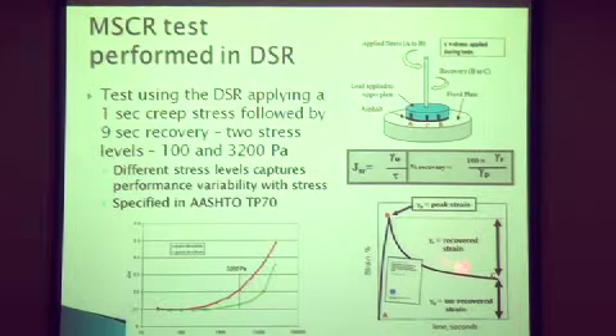Here you have your recovered strain, here you have your unrecovered strain. The J_nr is this strain, the unrecovered strain, divided by the stress. So compliance is strain divided by stress, whereas in modulus, it's stress divided by strain. We can also calculate the amount of recovery, recovered strain divided by the strain, as a percentage. Now here you see results for two binders.